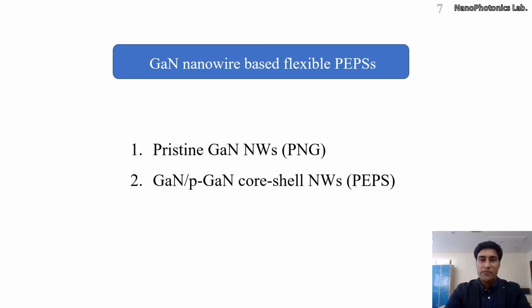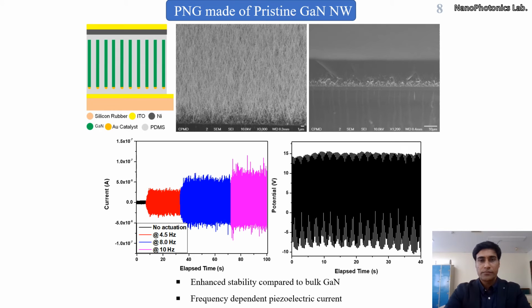So, GaN nanowire based flexible pressure sensors. Initially we fabricated the piezoelectric nanogenerator using the pristine GaN nanowires, and then we fabricated the homojunction GaN/p-GaN core-shell nanowires, and we fabricated the piezoelectric pressure sensor. So these are the results from the piezoelectric nanogenerator, which is based on the pristine GaN nanowires. And this is the structure.